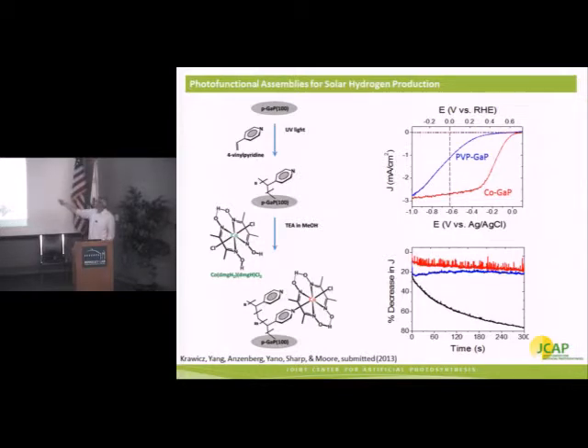Under illumination, when we just have the polyvinyl pyridine functionalized gallium phosphide surface, we do get a photocurrent, but it requires much larger potentials to be applied to the surface. Here, 0 volts versus the reversible hydrogen electrode means this is the thermodynamic potential for hydrogen evolution. So at that potential with the gallium phosphide with the cobalt catalyst, we are generating hydrogen with effectively no applied overpotential. In fact, we're doing that with an underpotential.